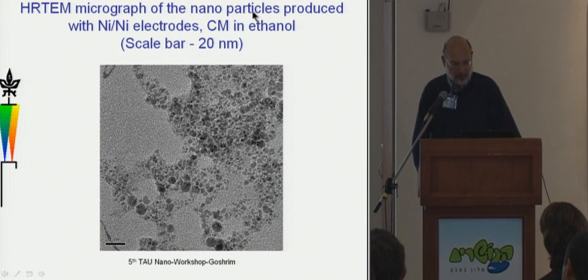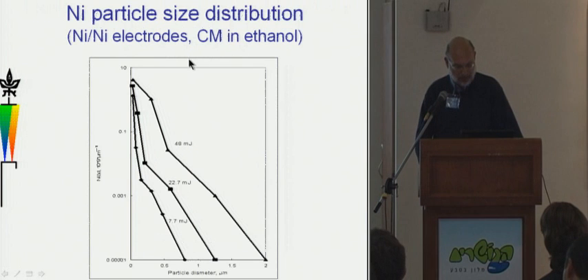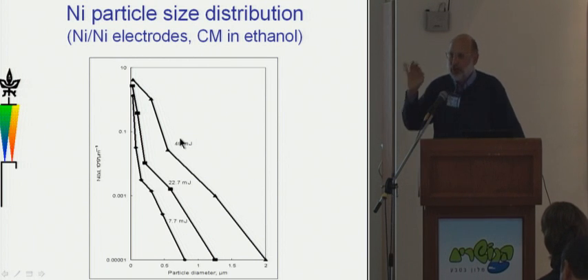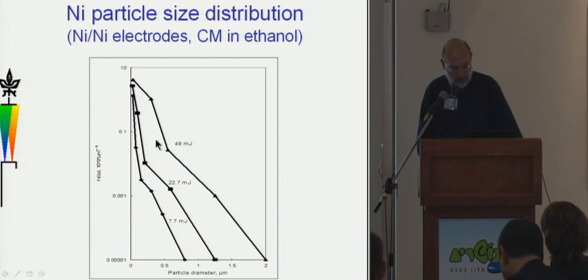These are some nanoparticles produced with nickel electrodes, contact mode, and ethanol. And perhaps one of the most important things here is that we unfortunately do not get homogeneous particles. We get a distribution of particles. This is the size distribution function as a function of particle diameter.